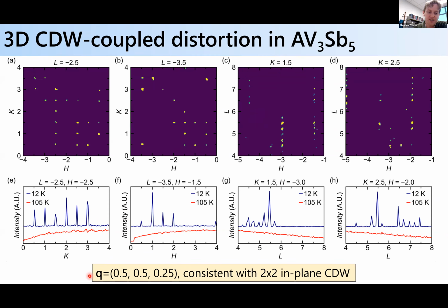system, our diffraction measurements are the same for half-half in the plane, but the out-of-plane wave vector seems to be half. So they're more consistent with half-half-half. So there seems to be some difference between the stacking sequence, the size of the unit cell below the CDW transition between the different systems, which suggests that perhaps this interplanar phasing is just some low energy physics that's pretty easily perturbed by whatever alkali metal you put in.